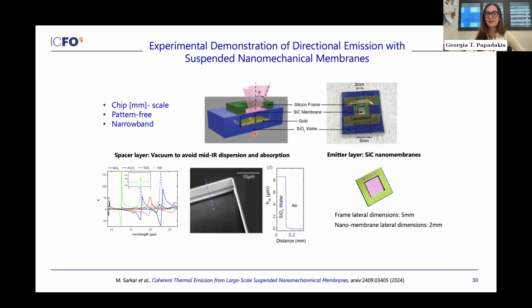So after struggling a lot with this, we actually decided to take a silicon wafer and etch a wedge out of it. And then we purchased commercial membranes from Norcada that are freestanding, and we placed them on top of the air gap. So this is how our devices look, and they are in the order of millimeters. So these are gigantic thermal emitters. And as you can see here, this is an AFM figure of the wedge that is exactly 8 microns thick.